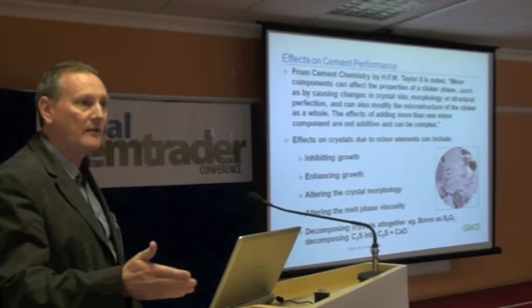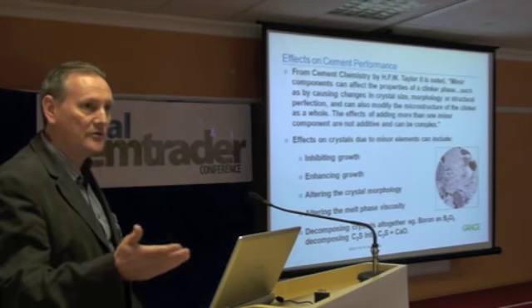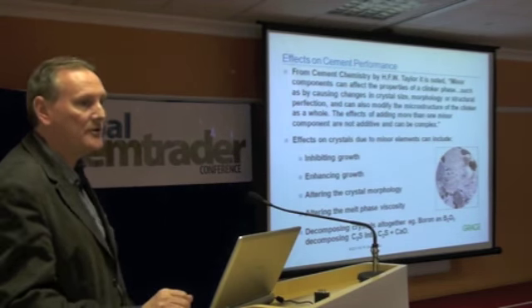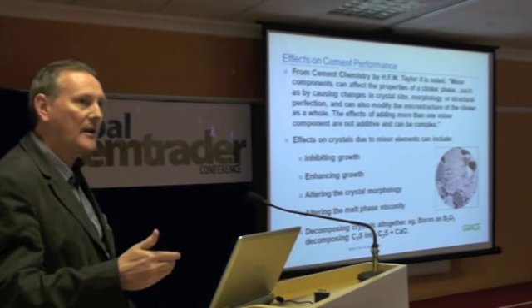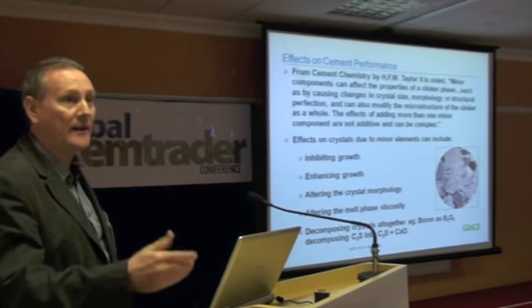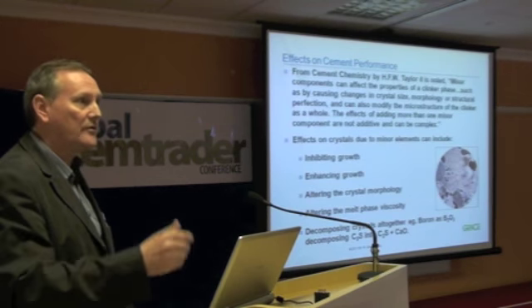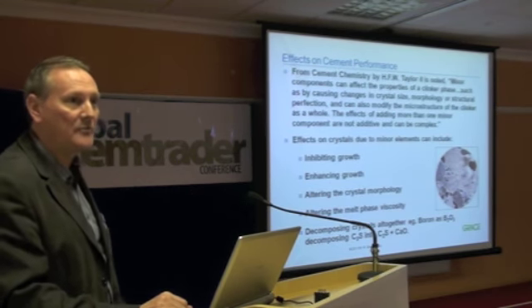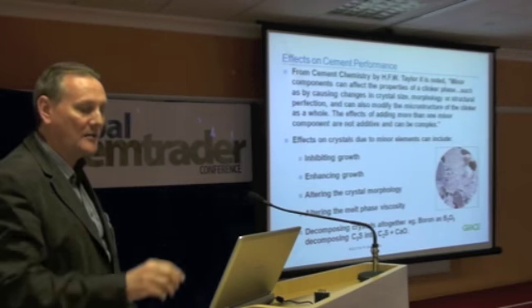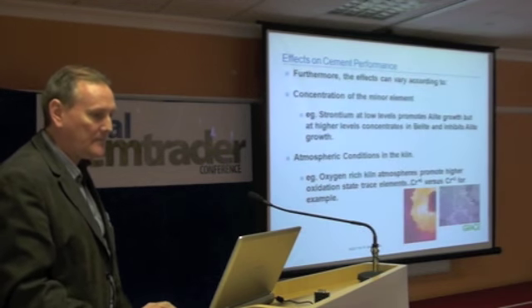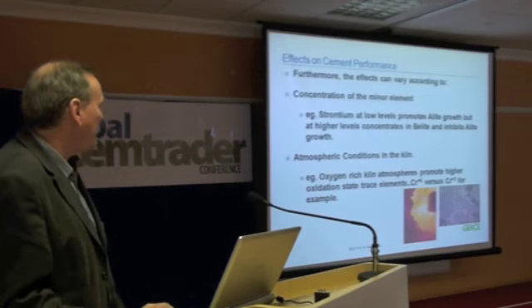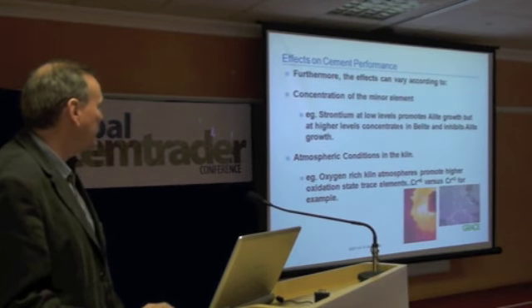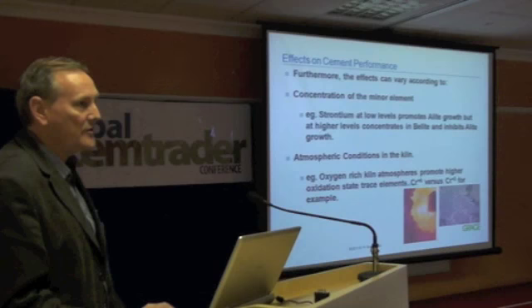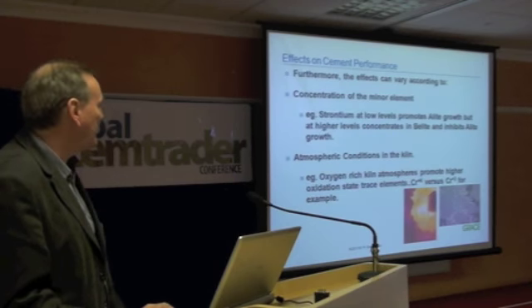But some minor elements, like phosphorus particularly, which is quite commonplace within the limestone deposits, above a certain level it can stabilise the B-lite so it won't react with the extra free lime, which causes a hell of a lot of problems for the person trying to run a kiln when he sees his free lime is still very high. The effects, of course, vary according to the concentration and the combinations, and also the way the kiln is burnt with the atmospheric conditions.